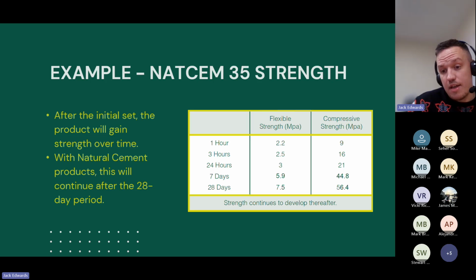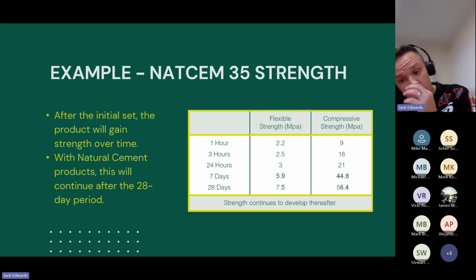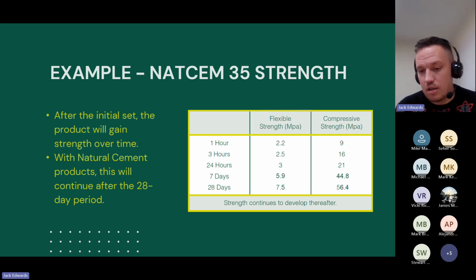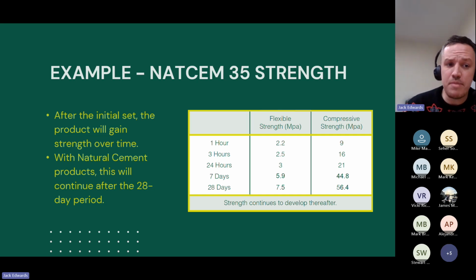So as well as the curing period and the initial setting time, there's also the degree of the strength gain after. So the strength gain will also be affected by the particular temperatures, which is why if you can accelerate that initial setting time by using warm water, that will kick in the strength gain sooner. This is just an example, again, using the same product, NATCEM 35.